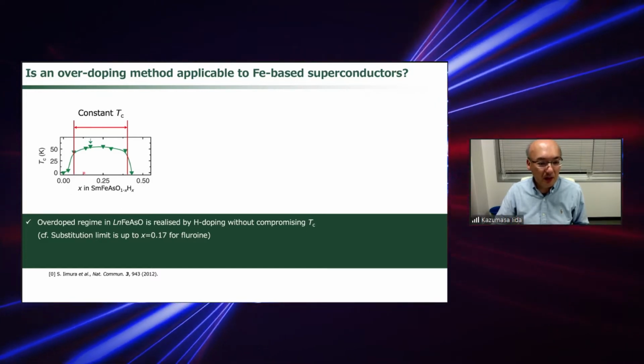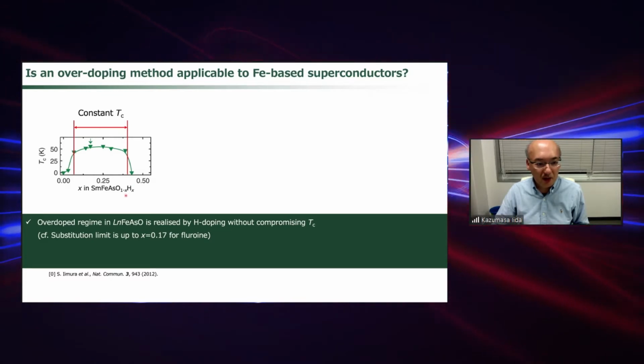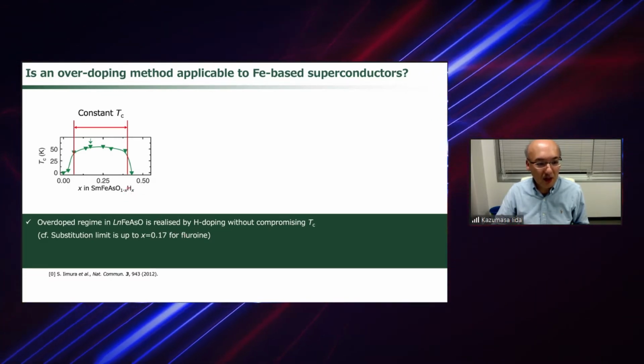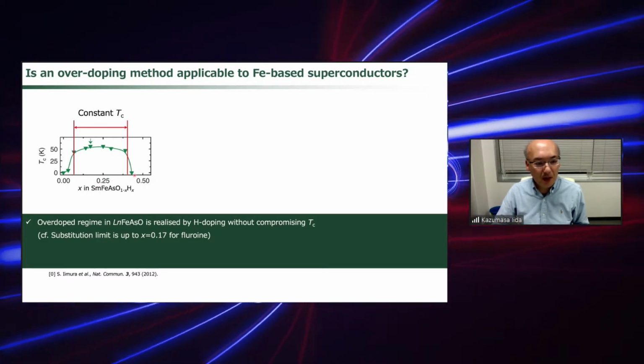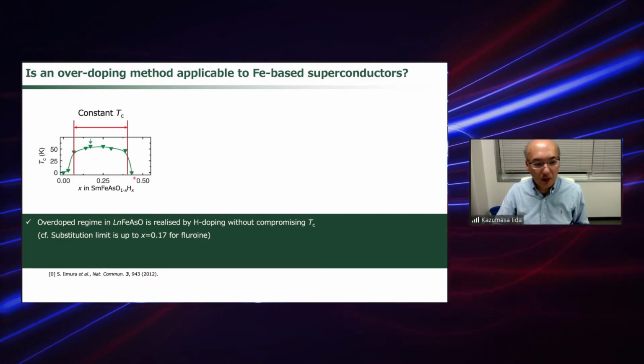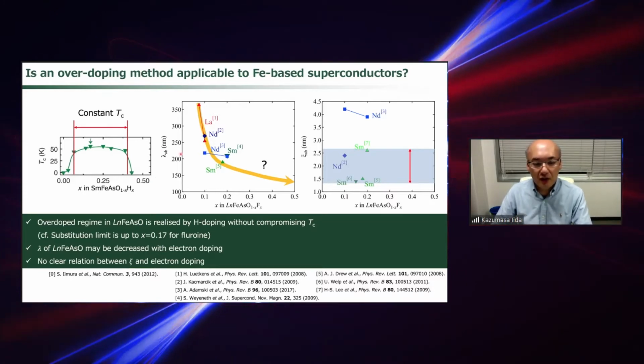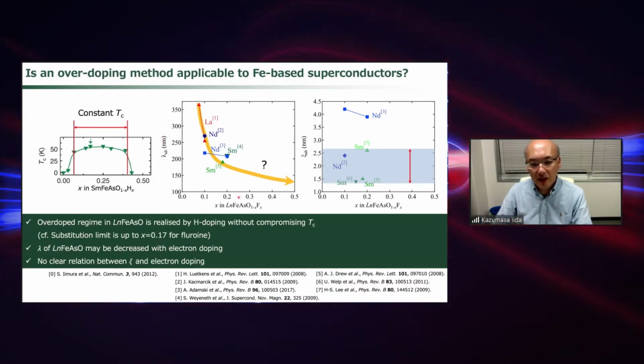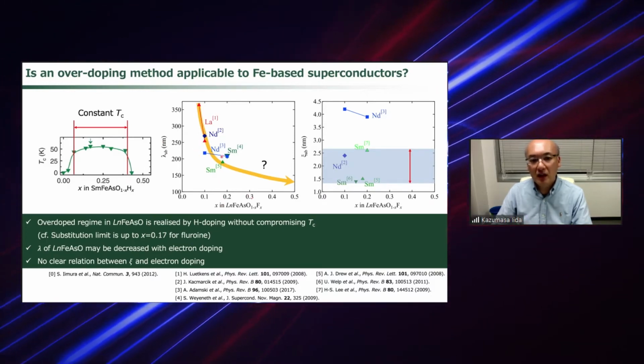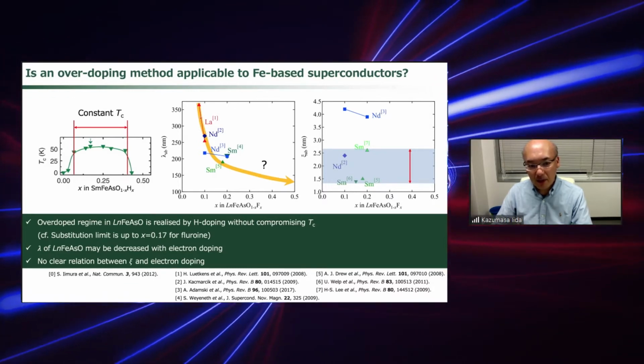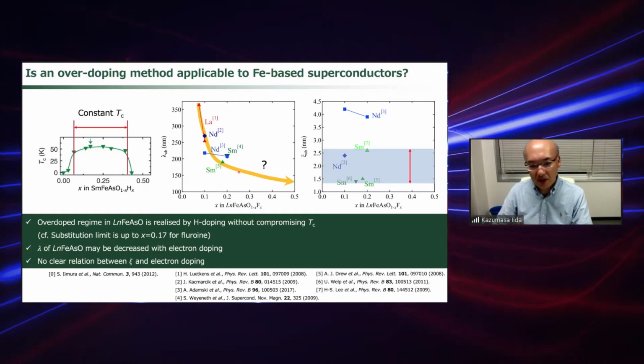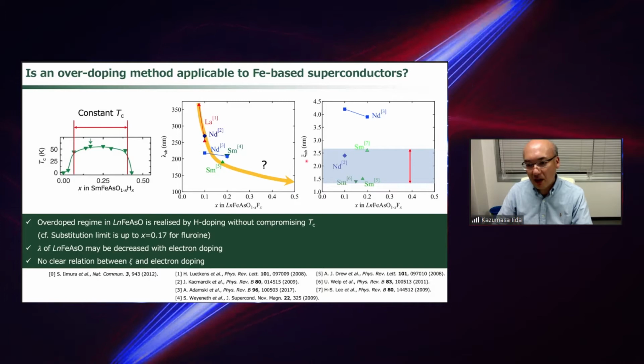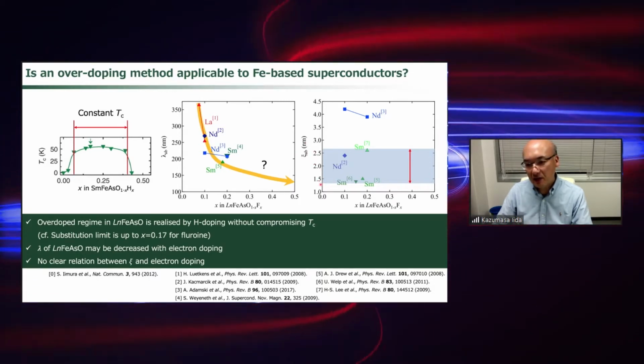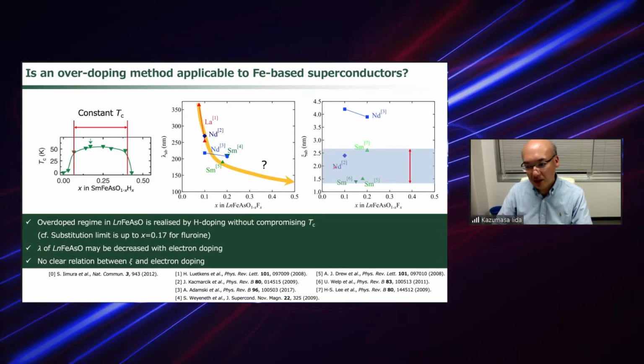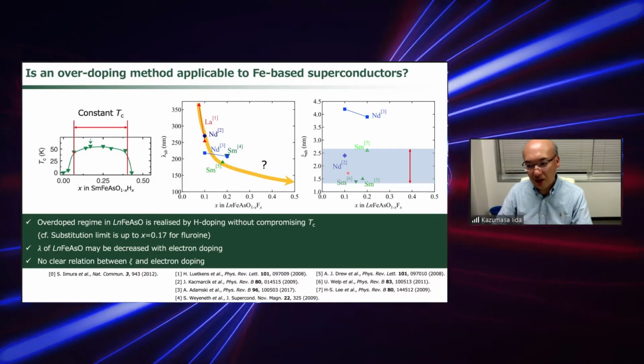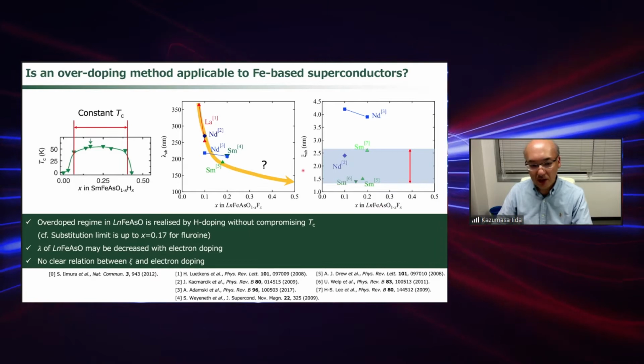The substitution limit is only 17%. But if you change the substitution element from fluorine to hydrogen, you can reach the overdoped regime up to nearly 40%. Here is a literature survey of the penetration depth as a function of fluorine concentration for the various lanthanide 1111 systems. As you see, the penetration depth decreases with increasing fluorine concentration, but the coherence length is in the range of 1.4 to 2.7 nanometers. That means we cannot see a correlation between the fluorine concentration and the coherence length.